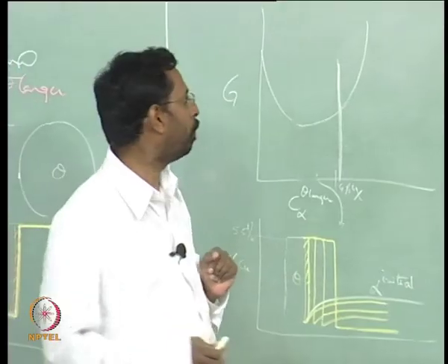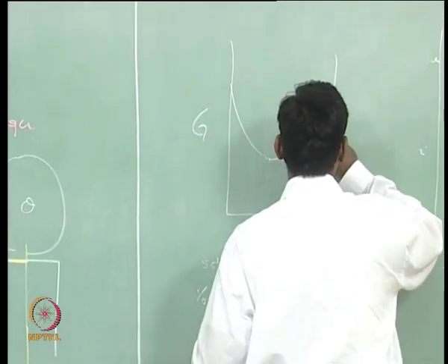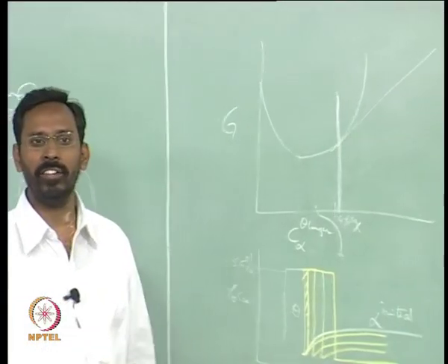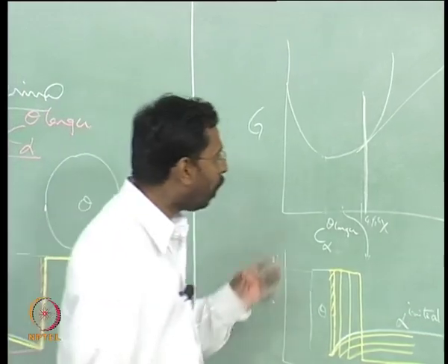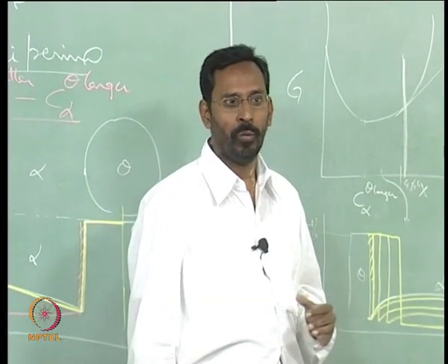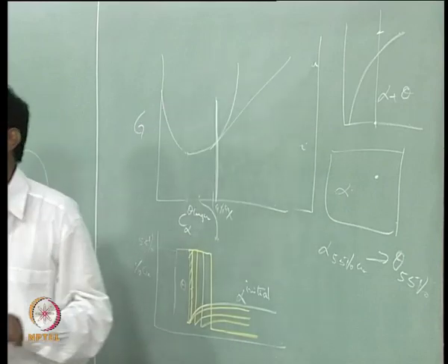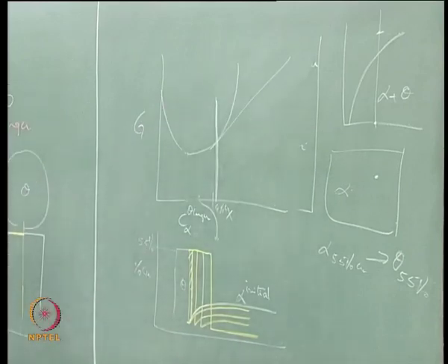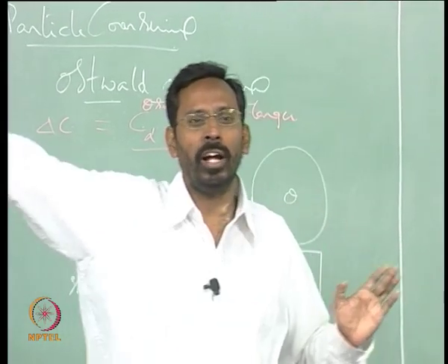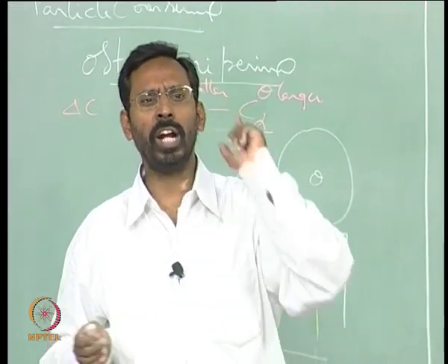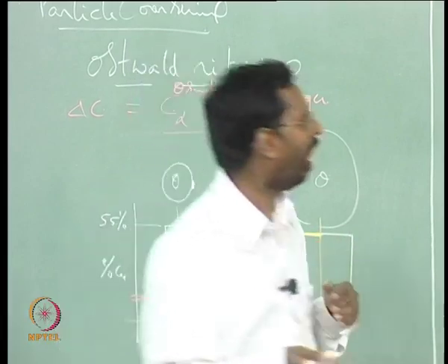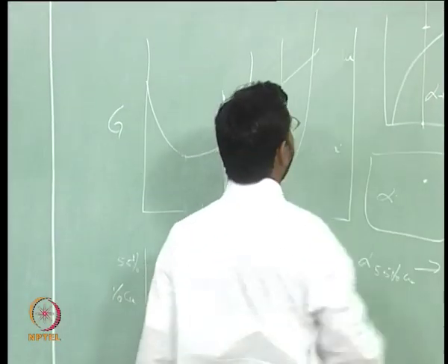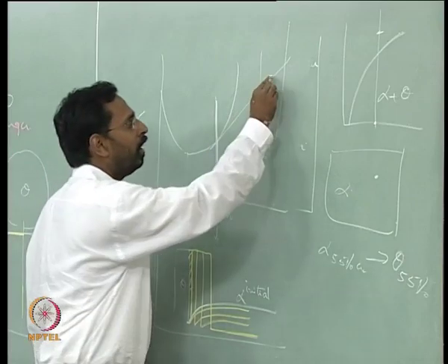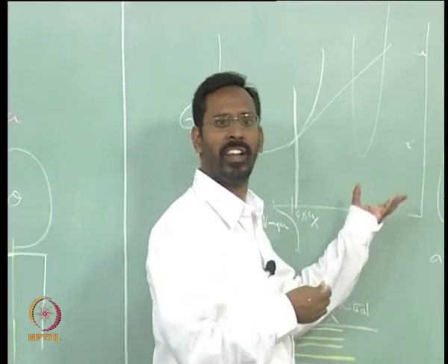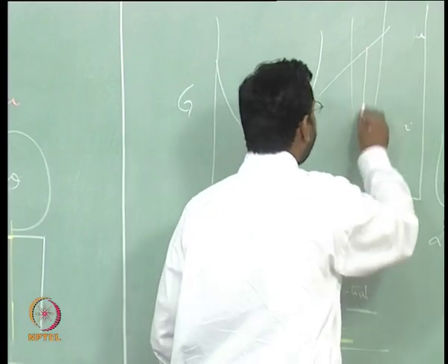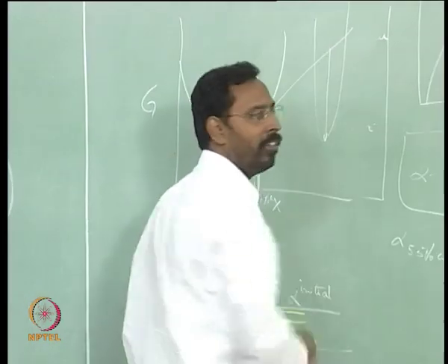How do you understand this precipitation? Simply draw a tangent. If I draw a tangent at that composition, then all the phases whose free energy is below the tangent can in principle nucleate. Let us not consider all the various phases that are possible, just look at only one phase, call it theta phase. At that temperature it has a certain free energy, and the moment there is a driving force, this theta will nucleate.